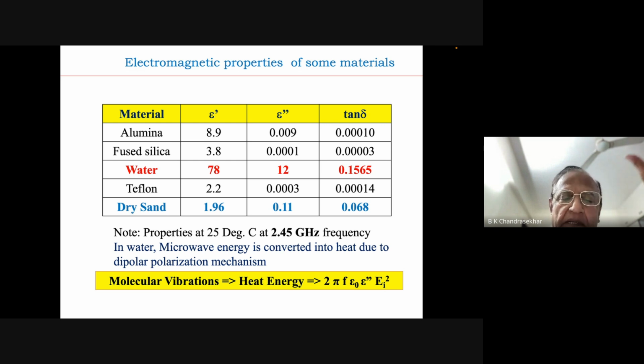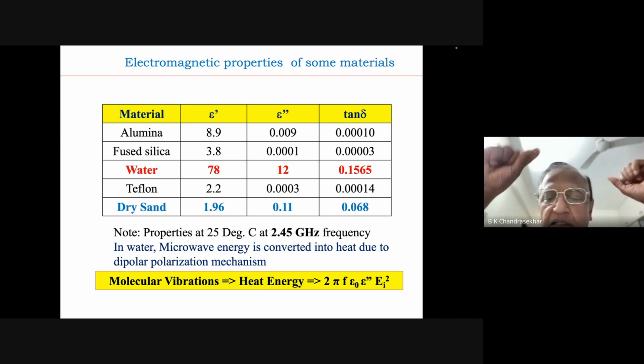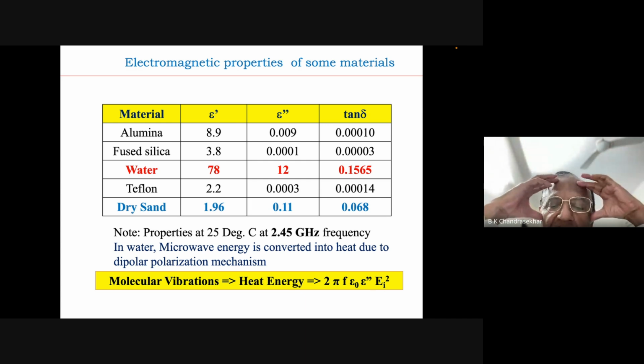Through calculations, people have found out the total amount of heat energy generated when you apply microwave onto a substance depends on the frequency F, in our case 2.45 gigahertz, epsilon double prime, and the electric field squared, which is basically the power of the magnetron. In an industrial microwave oven, we can smoothly increase the power from 0 to 100% to whatever value you want.